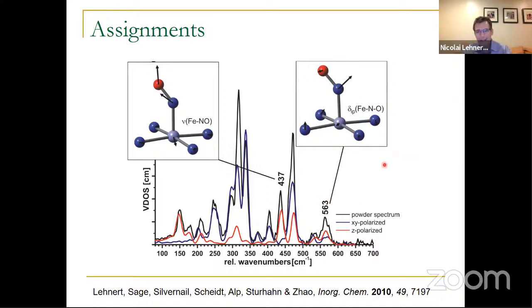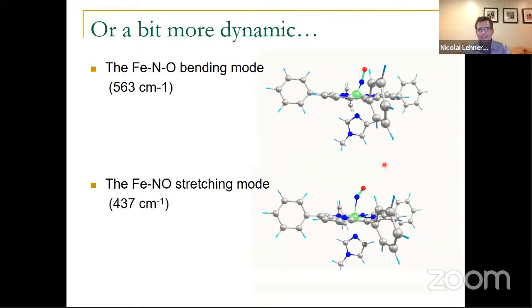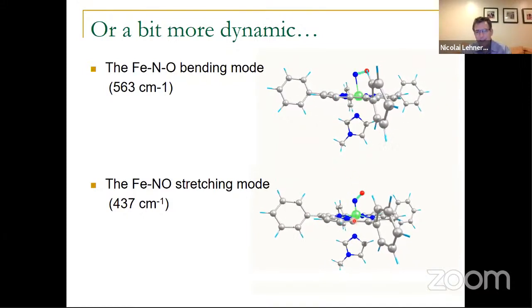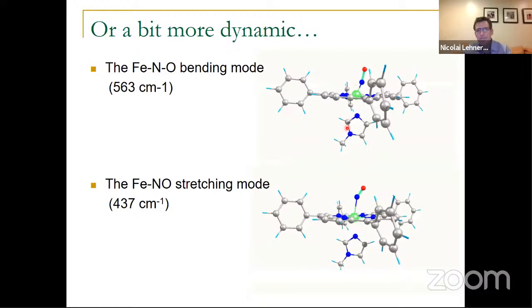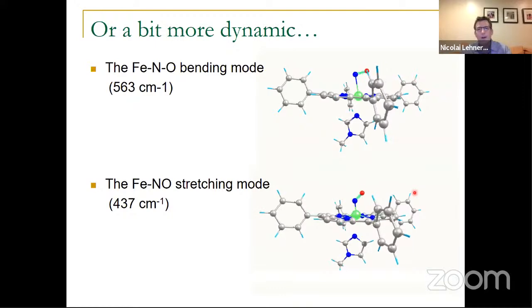And we can also animate that. So you can see here, you can see this a little bit better, right? So this is the stretching mode. You can see the iron essentially moves perpendicular to the plane of the heme. And you can see this is the bending mode. And you can see in the bending mode, indeed, the iron moves kind of in between, right? And in the bending mode, most of the oscillation is actually in the nitrogen. And this is the mode at 563. And these are the pictures that we will obtain from our simulation of the data. Okay, so